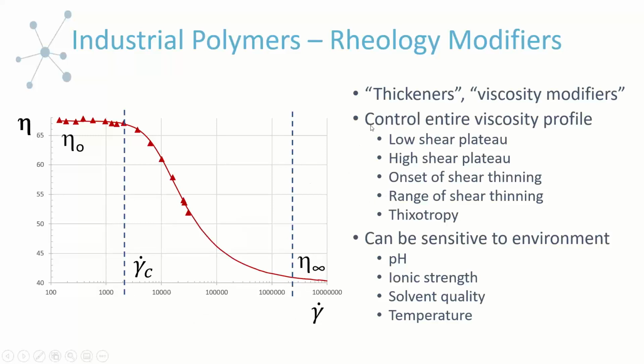And so if we're careful in choosing our particular polymer that we're using as a rheology modifier, we can really control the nature of this entire flow profile. By that, I mean the magnitude of both the low shear Newtonian plateau and the high shear Newtonian plateau. Also the critical onset, where does shear thinning occur? And then what is the range of this thinning? Over how many decades of shear rate does it take to bridge between the two plateaus?